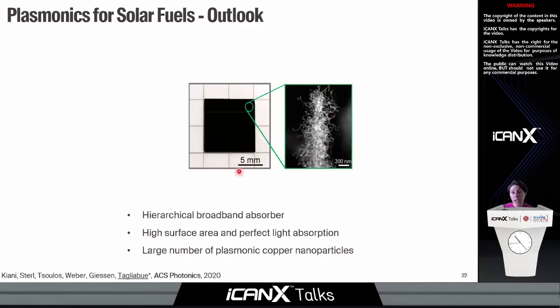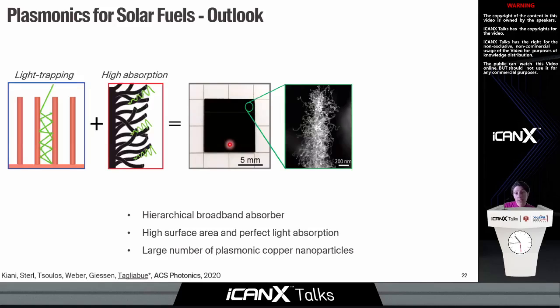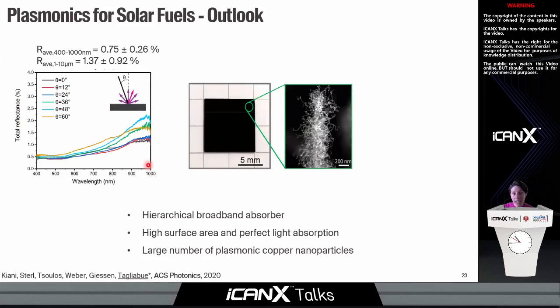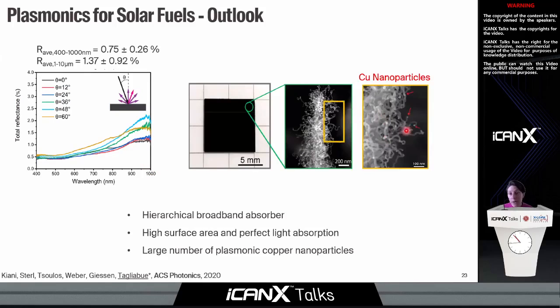In the first year, we have developed a hierarchical ultra-broadband absorber. This system is fabricated with a scalable synthesis technique, and it combines light trapping from a forest of copper nanowires with the high absorption due to carbon nanotubes that are grown onto it. With this, I'm coming to the conclusion. So this allows us to have very high absorption, and thanks to the presence of a small copper nanoparticle on the tip of each of these carbon nanotubes, we hope that this hierarchical absorber will be able to give us interesting results in terms of the CO2 reduction performance.